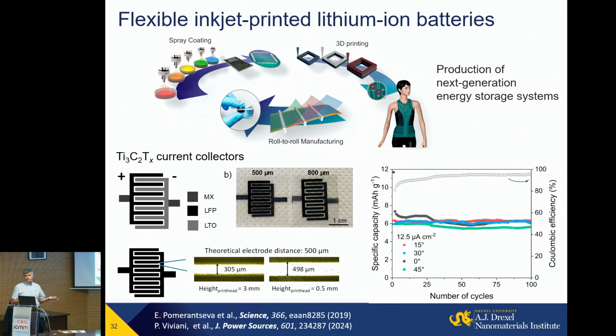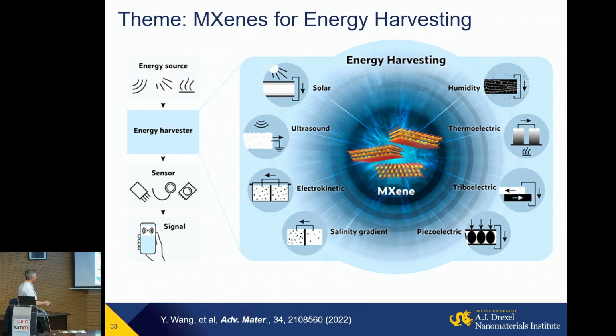And what is also very, very important, we all talk about flexible, printable devices, distributed electronics, Internet of Things. We can just make it an ink and print it on any surface. And those devices don't require a current collector at all because they are simply conducting. This has always been a major problem with making printable devices because people typically have to put a metal current collector, which is very difficult to deposit onto any surface because it usually requires vacuum, electron beam, or etching of metal foils. And here you just go and print it and let it work.